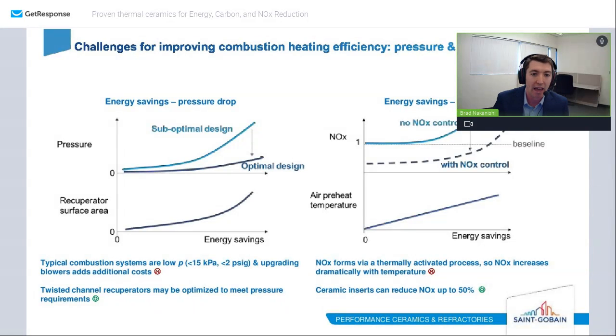On the left, as energy savings is increased, the recuperator surface area increases, which in turn increases the pressure drop of the overall combustion system. Typically, blower systems operate at low pressure, and upgrading adds additional costs. Fortunately, twisted channel recuperators may be optimized using computational modeling to minimize pressure drop and avoid blower upgrades while providing additional energy savings. On the right, reducing energy consumption by recuperation increases the preheated combustion air temperature.